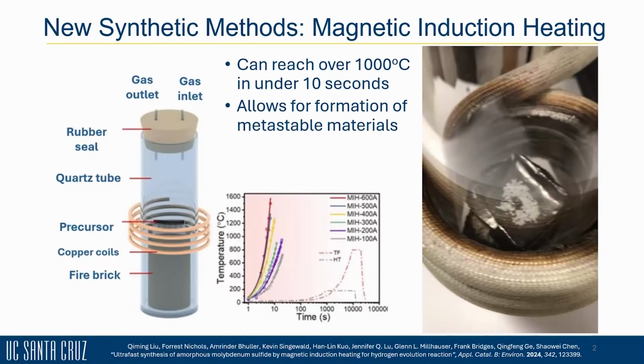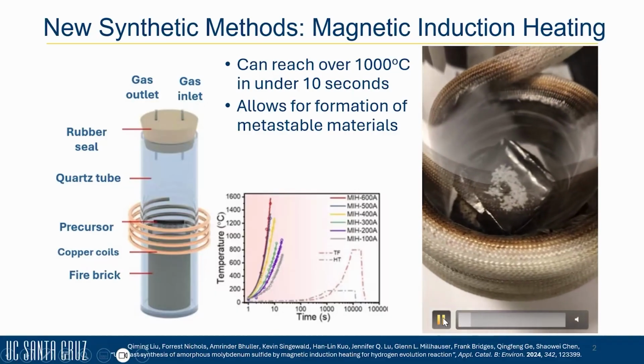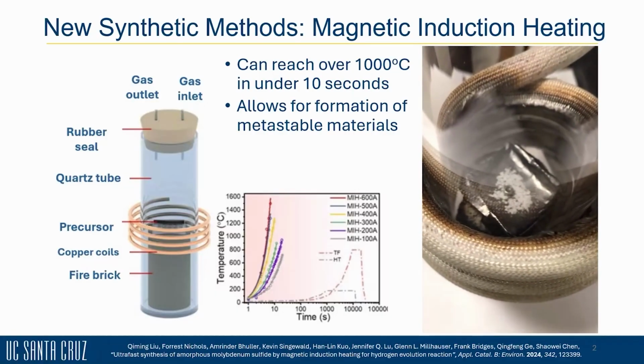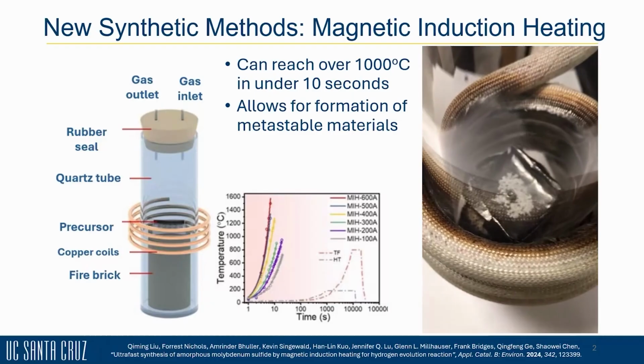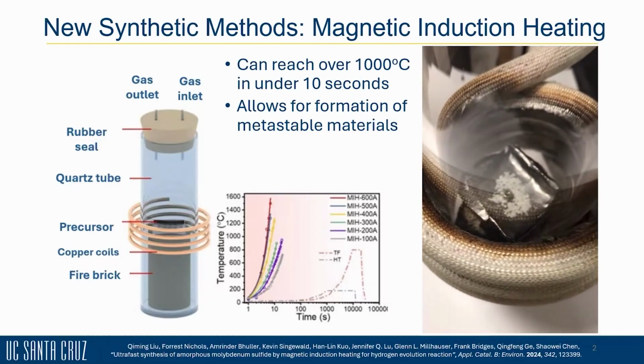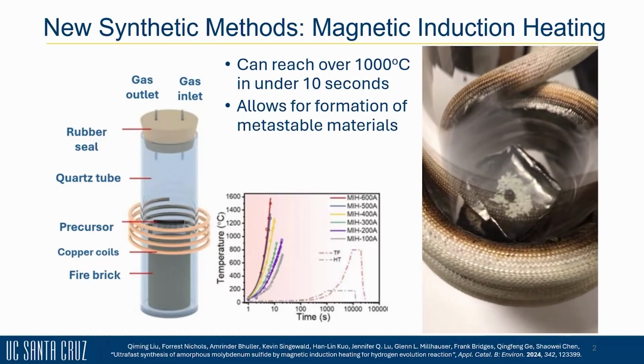To get around this, in the Shaowei Chen lab, we've been utilizing a new fast synthetic method known as magnetic induction heating. In the video near the right, you can see a metal reduction process that typically takes several hours completed in only 10 seconds, when that white powder turns into a black powder.